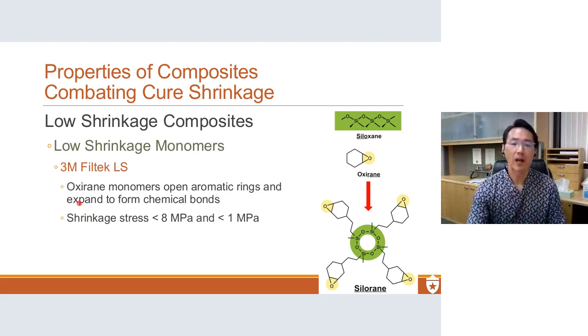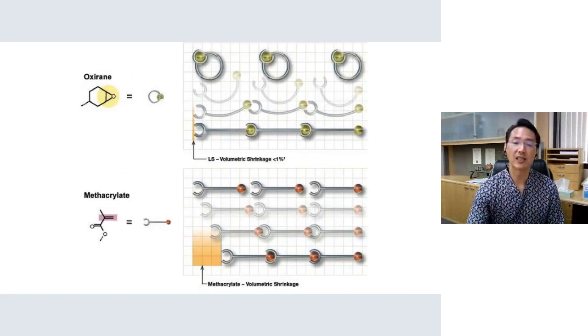3M had a product called Filtek LS, which is not a methacrylate. It is actually an epoxy system, okay? And they developed a more biocompatible, hydrolytically stable initiator system to be able to use epoxies. Basically it's a siloxane plus an oxirane. Oxirane is another word for epoxy. And now they have 4 functional groups you can see here. And it's the oxiranes that react. When they react, this ring opens up to give it some expansion to counter the contraction. And so their shrinkage stress is less than 8 megapascals, and depending on the formulation, less than 1.